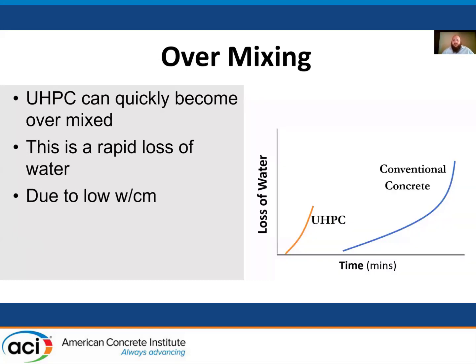So I learned very quickly you can overmix stuff too. This is just an illustration. These aren't real numbers, but I've seen numbers like this where you start at the y-axis where it intersects zero of time. That's when it stops mixing, whenever it's ready to mix. And then if you keep mixing, eventually with this UHPC there's going to be a rapid loss of water, and slump's going to go down quite a bit. It's kind of crazy how quickly that occurs compared to maybe a conventional concrete mix, which can take much longer than that. And again, when you have a lot less water, this is going to happen.